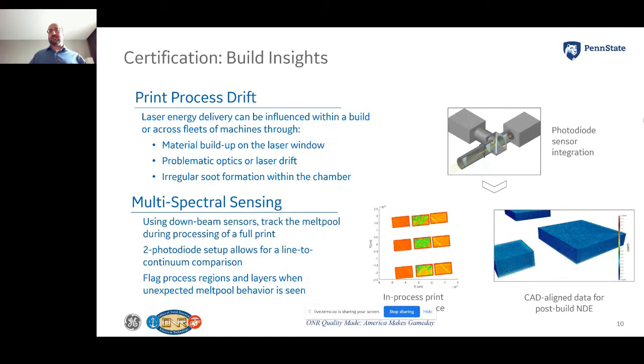And then in addition to this, we've also developed with Penn State a calibration procedure for this. And actually that led to the gas flow sensor that was shown previously, a way for us to get a calibration module within the chamber unobtrusively so that we can get the right information to level set the sensor across a fleet of printers and also a printer over a long period of time. And what this provides us with now is a calibrated data set for each print that we can then understand the impact towards process variations and inform NDE experts around changes in that process and where and how they occur.